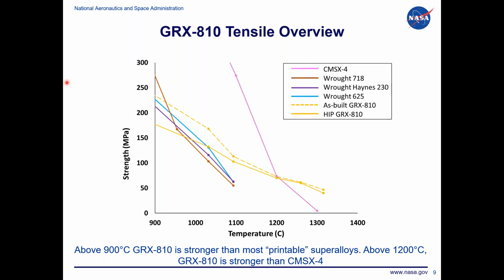We've also done mechanical testing for a multitude of properties, which I'll discuss, but we've also taken tensile properties all the way out to almost its melting temperature. In this case, 1316 degrees Celsius. And I like this figure because it does give you a sense of when GRX-810 starts to become stronger than other conventionally used superalloys. When we're picking on the conventional 3D printed alloys like 718, Haynes 230, 625, it's really between that 900, 1000 degrees Celsius where you start to see GRX-810 become significantly stronger.